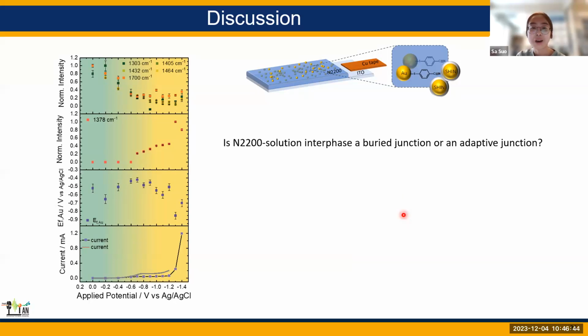And for our interest, we really wonder a question, which is: is the N2200 solution interface a buried junction or an adaptive junction? A buried junction just simply means that there is no ion permeable into the film, but the adaptive junction will allow the ion to permeate or penetrate into the film.